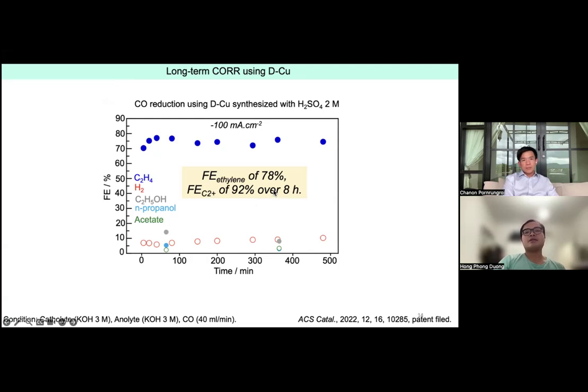And I have to say that this result significantly highlights the importance of CO reduction over CO2 reduction. Since by CO2 reduction, you can get plenty of products like formic acid, CO, or methane, which means a very large part of your current density or your electrons will go into those products, and then we have to think about the way to extract them and make them more useful later on. But on CO, we primarily get the C2+ product, and we don't get any C1 products in this case.